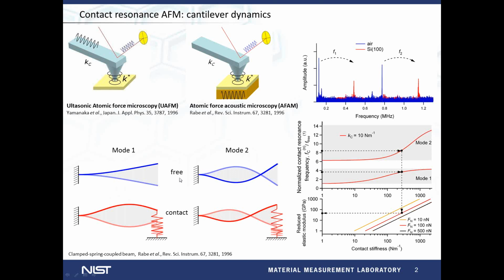And intuitively, we can look at the elastic tip-sample contact like a spring attached at the end of the cantilever, and this tip-sample contact spring modifies the boundary condition at the end of the cantilever and induces a shift in the resonance frequency of the cantilever, so it modifies the dynamics of the cantilever. Of course, the contact representation becomes more complex if we have to consider the damping, lateral couplings, and so forth. But for elastic modulus measurements, what we are looking primarily is to measure the shift in the resonance frequency of the eigenmodes of the cantilever from the free values to the contact value, and then use a clamped-spring coupled beam model to convert these resonance frequency shifts into